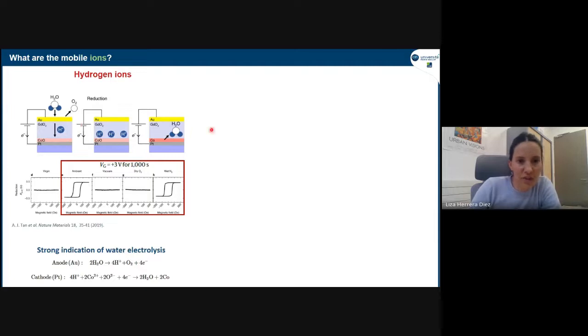They could nicely show this: here's the virgin sample. If they apply a gate voltage in ambient conditions, they get this perpendicular state. If they do it in vacuum, they don't get the effect. If they do it in dry oxygen, they don't get the effect, which is important to back up the story about this being hydrogen and not oxygen. But if they do it in a nitrogen atmosphere with some water inside, then it's PMA again. So they could really show that this is related to hydration, to the water, an exchange of hydrogen with the water from the atmosphere.